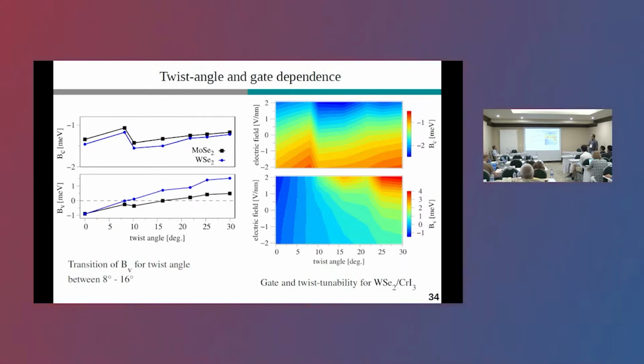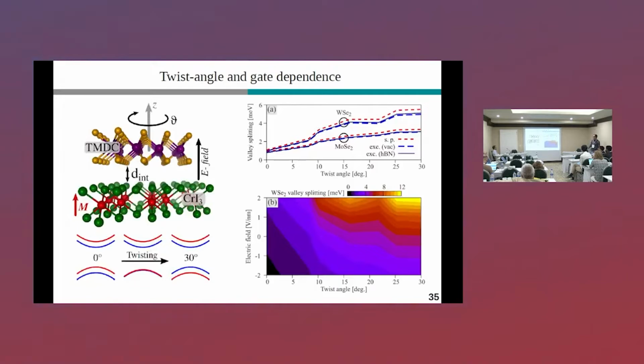And if you look into this electric field and twist angle dependence, you can find that the conduction band splitting can be tuned in the range of -2.5 to -0.5 millielectron volts, while the valence band splitting can be heavily tuned from about -1.5 to 4 millielectron volts upon twisting and gating. And this has profound consequences for the valley splitting. So the most important result is here. This is the calculated valley splitting of tungsten diselenide on top of monolayer chromium triiodide when we twist and gate.